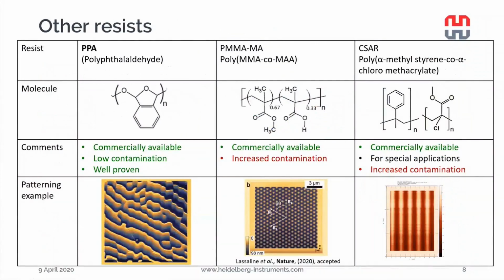So what else is out there other than the PPA that has all these nice points? We have seen a lot of resists that have been tested, like PMMA copolymer, that's also commercially available, but it shows a bit of increased contamination compared to polyphthalaldehyde. But nonetheless, Nolan Lassaline, who also had a recent webinar, had a quite good success with this resist and was able to pattern his Fourier surfaces quite well, from what I've heard. Then there are other resists like Csar. It's also commercially available from Allresist, that can be used for special application where you need to use different solvents, but it also shows increased contamination.